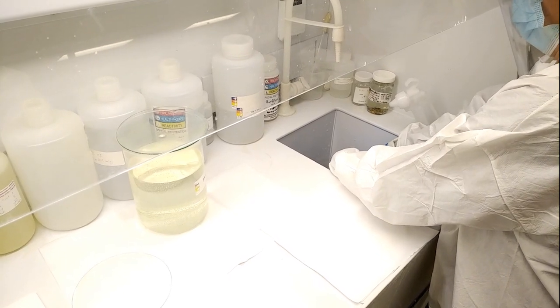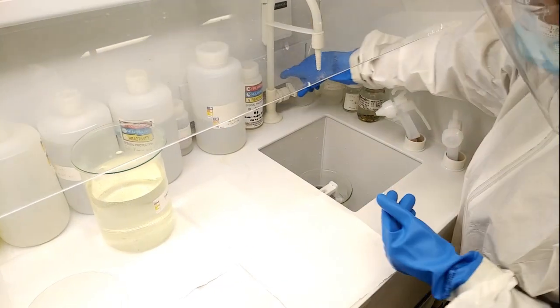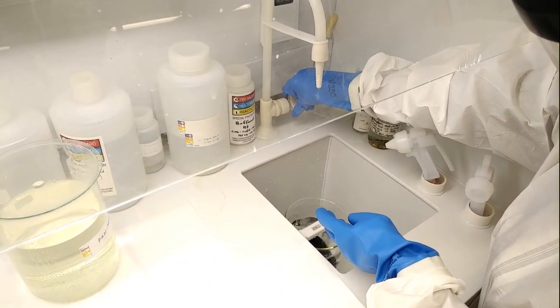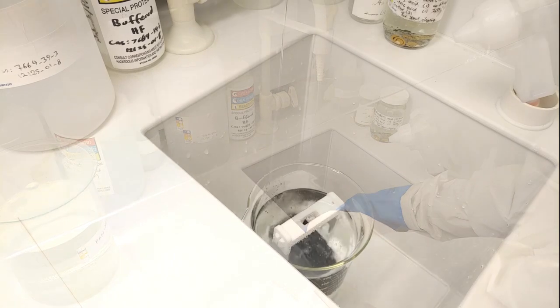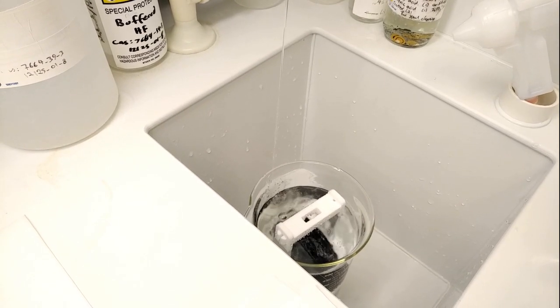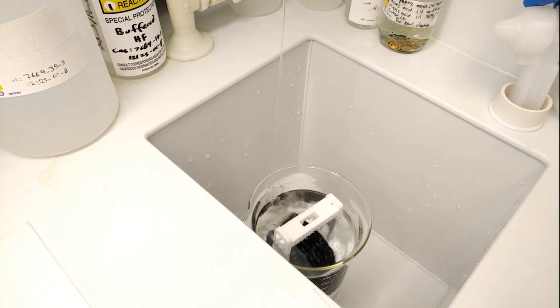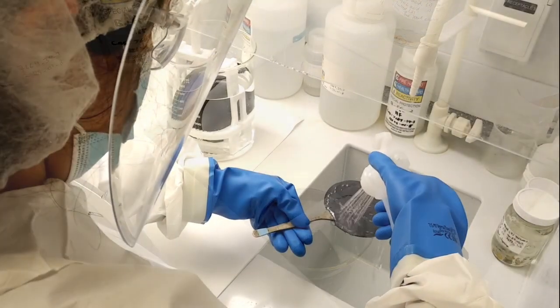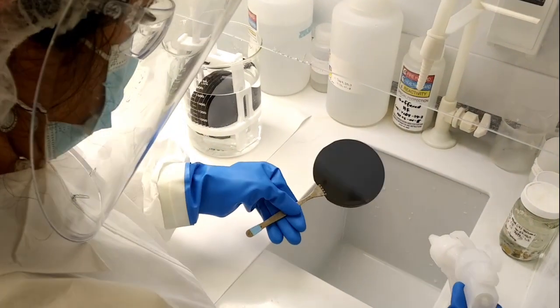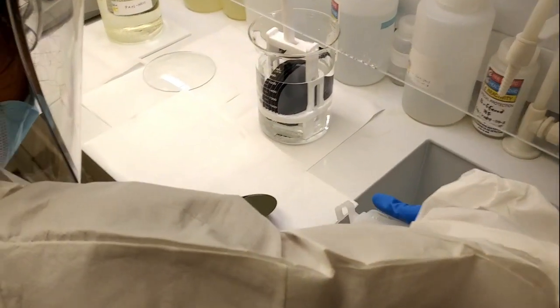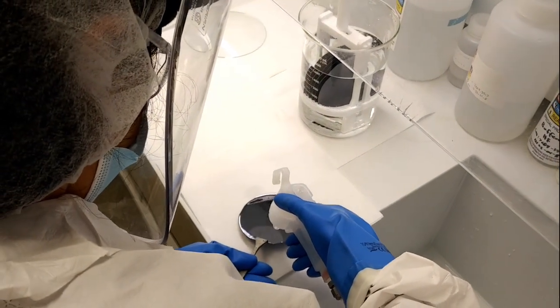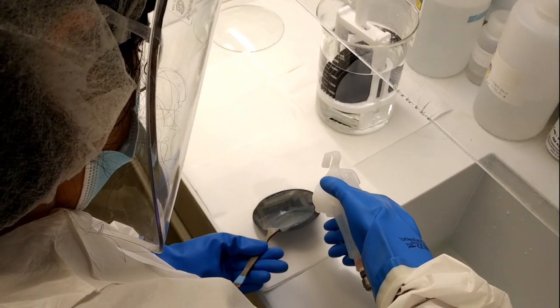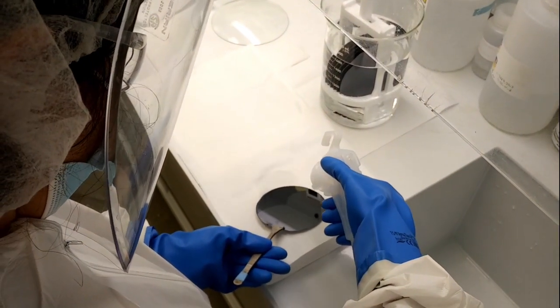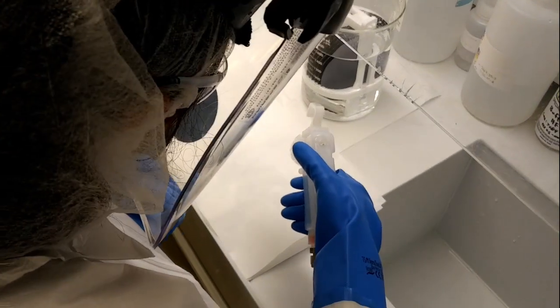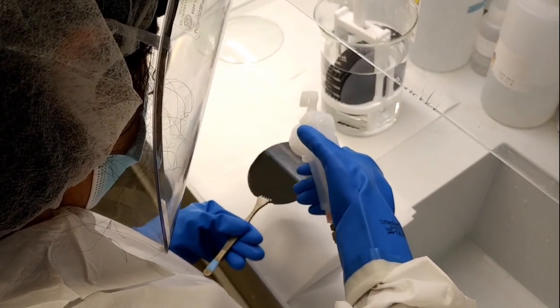After about 20 minutes in the RCA solution, deionized water, or DI water, is slowly added to dilute and cool the solution. The wafers are then carefully washed with DI water and then dried with clean dry air. With all the wafers clean, they are ready to be put in the furnace to grow the oxide layer.